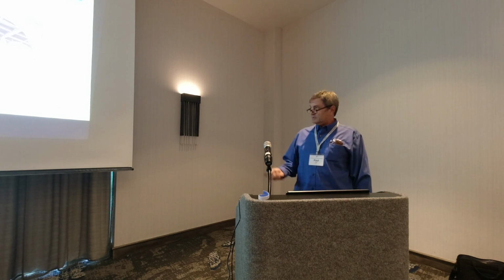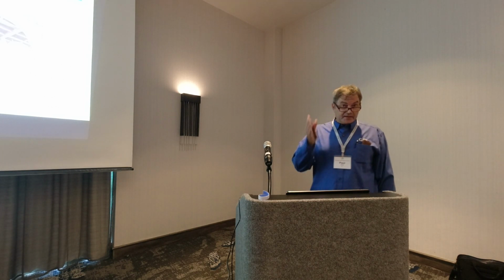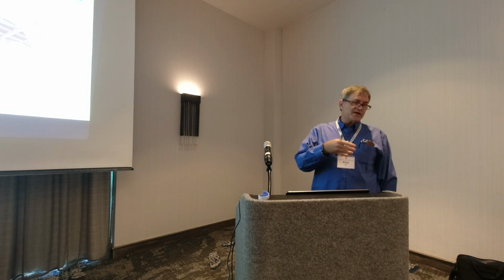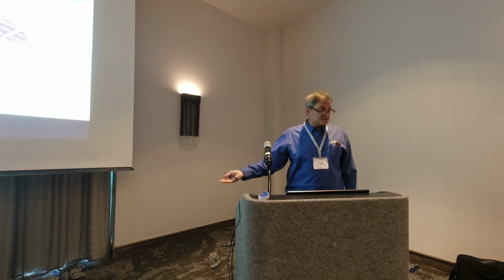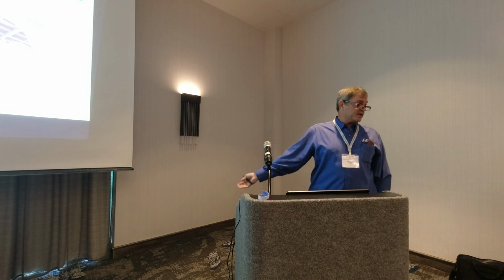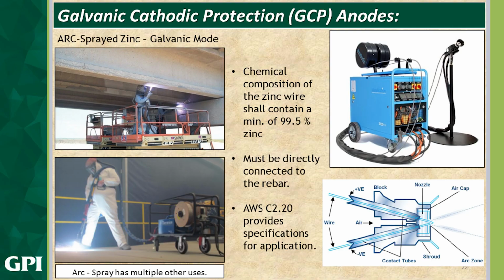So it's just flame spraying zinc onto concrete, essentially, and then connecting that flame spray either to an ICCP system or to a galvanic system. Some of the equipment involved and the technology, here's a guy actually doing it. We've got the 99.5% zinc. It's got to be directly connected to the rebar, and AWS C2.20 provides the specifications for application.